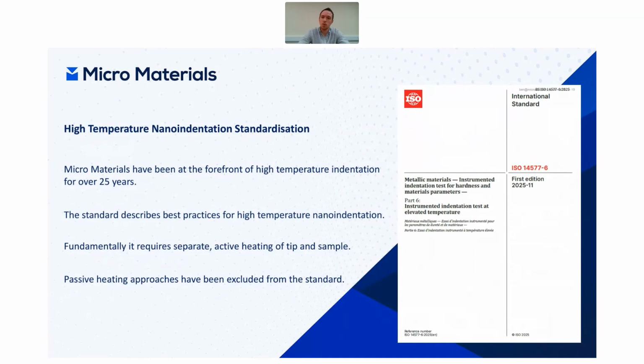Following on from that, we now have the first edition of the ISO standard for high temperature nano-indentation. As you can see here, this was released just earlier this month. This is ISO 14577 Part 6, instrumented indentation test at elevated temperature. As some of you or many of you may know, Micromaterials have been using or developing the high temperature indentation capability of our nanotest for well over 25 years. And in that time, the technique has developed and matured to the point now that we have this ISO standard. So Micromaterials, and in particular my colleague Ben Beek, has been working on the committee to draft this first edition.